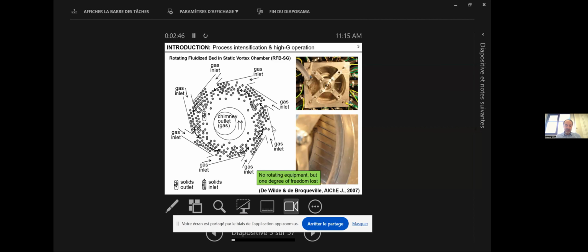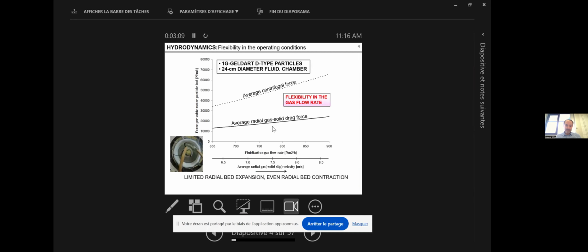And so in drying, there are publications. I don't have the time to go through all those publications here, but we demonstrated that you can reduce the size of the equipment for same drying capacity, same drying quality, with about 1 order of magnitude. And we dried all kinds of materials. And then for coating, let me show a few slides.